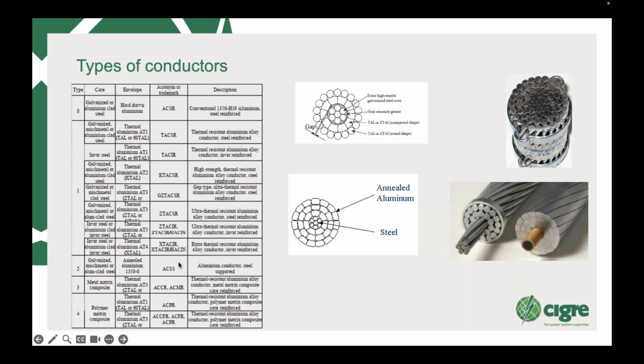Another one which is very common is the ACSS, which is a high temperature, low sag conductor. It's an aluminium conductor which is fully annealed, so it only depends on the steel core to carry the load. Then you get what's called here, and these are the different types according to IEC, type three, which is a thermal resistant aluminium alloy with a metal matrix core, developed originally by 3M. This has a particular core, which is a metal matrix, which doesn't sag. So that's a high temperature, low sag.